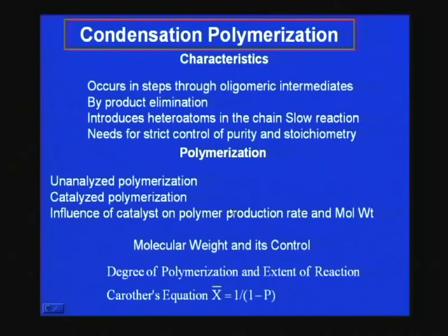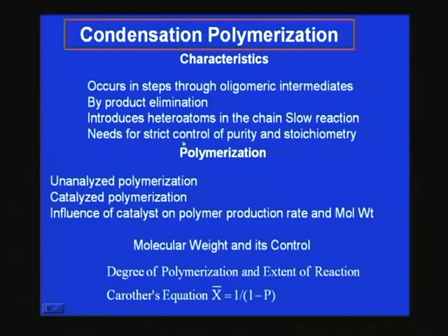The polymerization reaction is slow. It takes a long time to complete, to get a polymer product. And one most important parameter is that this kind of step reaction polymerization, polycondensation reaction, needs a very strict control of purity and reaction stoichiometry.